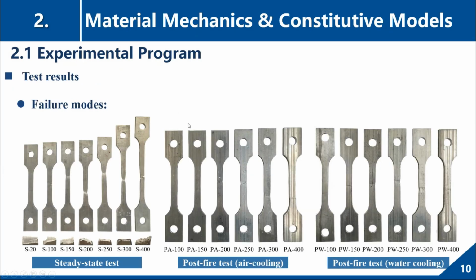And these are the failure modes. We can see that for the steady state tests, when the temperature rises, the ductility and deformation capacity become better. But for the post-fire tests, the deformation capacity remains almost the same.